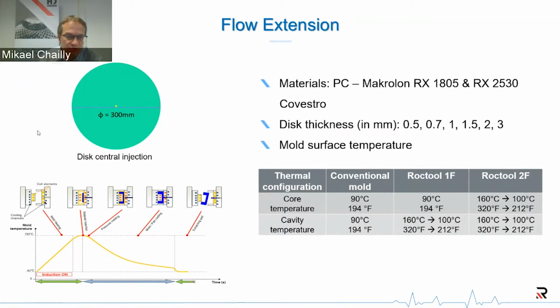Just a small reminder about how the Roctool process is normally configured in injection molding, as you can see on the graph on the left. We start to heat up the mold surface whenever the mold is open and there is no plastic material in it, and we stop heating normally before closing the mold. During the close, we wait a few seconds more to let the heat diffuse from the inductor position, where the heat is generated, up to the mold surface.